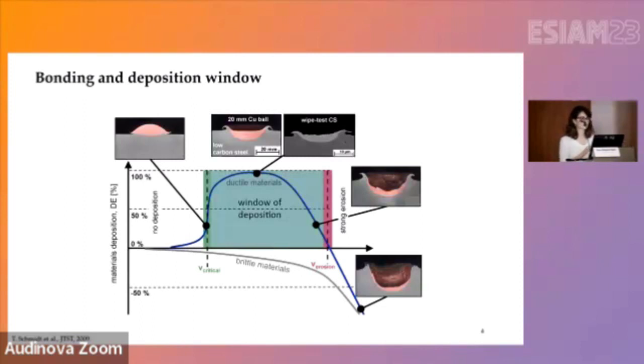Before that, just a few words about what happens during bonding in cold spray. We normally need to reach a special window of deposition, in terms of the range of velocity, in order to ensure that the particles are bonding. At velocities lower than this critical velocity, which is a function of thermomechanical properties of the material that we are spraying, we have the rebound of the particle. Then we would start bonding at critical velocity. Slightly higher than critical velocity, we can get to full deposition efficiency. It means that all the powder that we are depositing would fully adhere, so we are not losing any powder during the process.